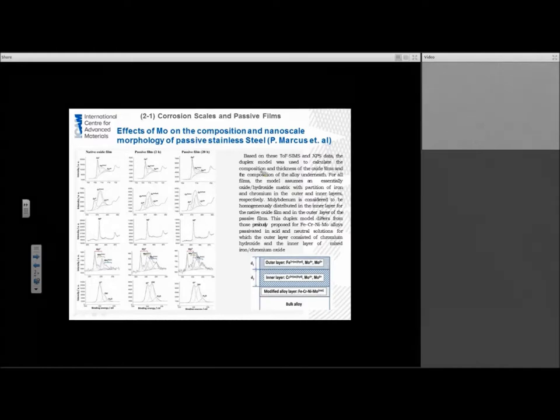Another thing that Philip has been able to do is he's been able to combine the ToF-SIMS data with some XPS data. The XPS data that he has used has shown that molybdenum is very much so present in the oxide layers, predominantly in the inner oxide layer. If you take a look at the schematic, this is the model that Philip proposes, in which you have an iron-rich outer oxide layer with some moly 4+ and moly 6+ incorporated within the material, as well as an inner oxide layer that is chromium-rich. And again, that will have moly 4+ and 6+ within it.